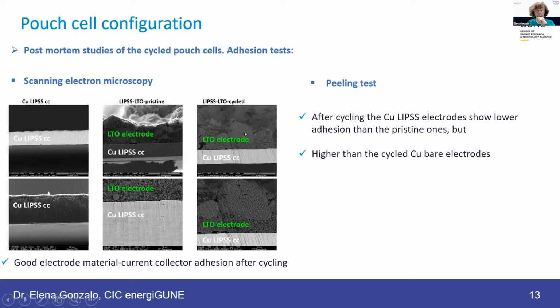Here you can see the images of the cross-section of the electrode that was cycled, and even if it was suffering a stress of charge and discharge, or applying a current, the adhesion was perfectly fine after cycling compared to the pristine electrode.